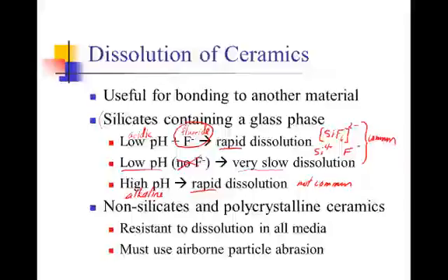We can avoid having acidic pH and fluoride present at the same time by using a neutral fluoride whenever we have ceramics in the patient's mouth. However, hydrofluoric acid has acidic pH and fluoride ions together, and that is used on purpose as an acid gel to etch ceramic restorations in dentistry.